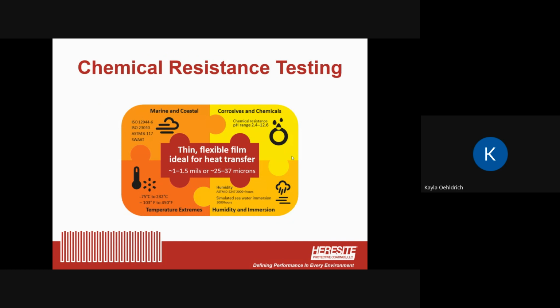So we spend most of our time, and we have the most data, on chemical resistance testing. These tests deal with corrosive environments, like it says up in the upper right-hand corner in the yellow quadrant. But many times it's impacted by those things there that are around it. There's an infinite number of chemicals and environments and different concentrations and temperatures, humidity levels, that are out there. It's unlimited. We can't test everything, but we have enough information and a wide range of results where if we don't know exactly, if it's been tested in that area, we can offer a pretty good idea on how that coating might do.